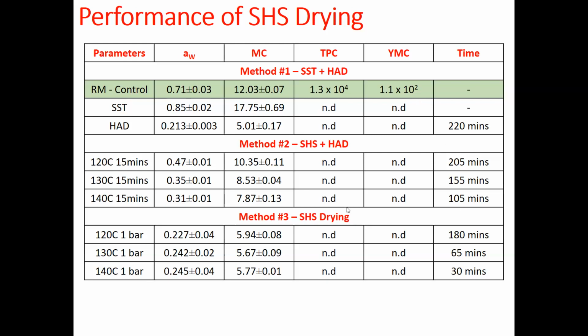If you compare superheated steam drying, the combined microbial inactivation and drying process, at 120 degrees C, 1 bar, 130 degrees C, 1 bar, and 140, you will get an almost constant, or average, water activity and moisture content. As you can see, it's not much of a difference. But the processing time is very, very low. At 140 degrees C, the processing time is only 30 minutes, in comparison to the same result where the TPC and YMC are at a non-detectable amount, which takes about 220 minutes.